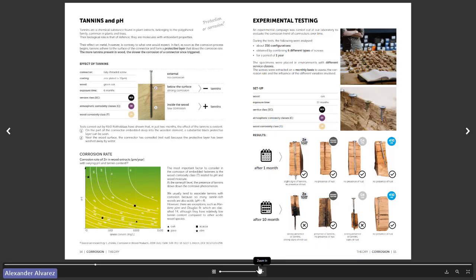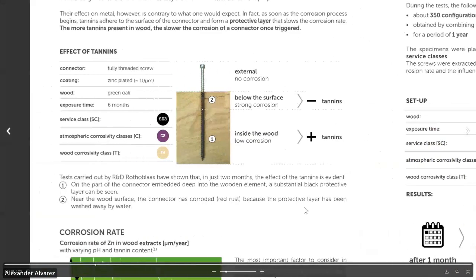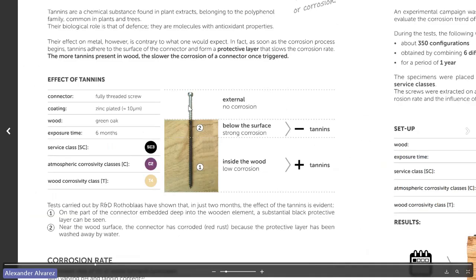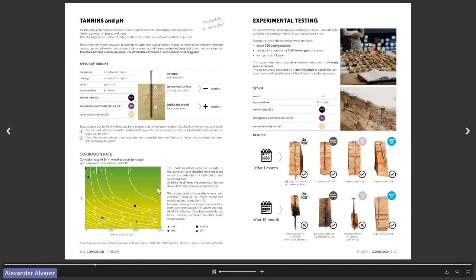If you can see on this picture right here, you can see what happened to one of the screws that has been inserted into the wood. You can see that for the top layer, there's no corrosion. It was external, but as you go more and more in, you start seeing the coating change, and you start seeing more corrosion happening. This doesn't always depend on the pH level of the wood species. Sometimes it's not a perfect correlation. Sometimes it depends on the wood species itself.